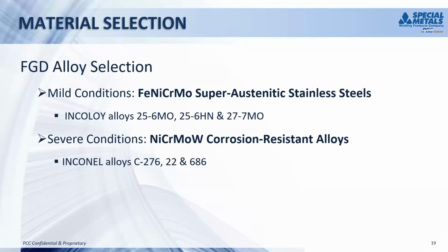But in the severe areas, the outlet ducts, inlet ducts, and the chimney flues, those just almost always have to be fabricated from a nickel base chrome moly tungsten type alloy. Alloys like C276, 22, and Inconel 686 is our most highly alloyed, most corrosion resistant material. And it has found applications within FGD systems.